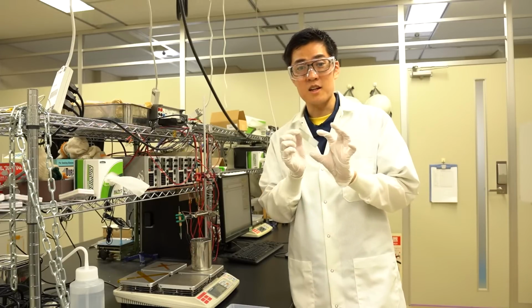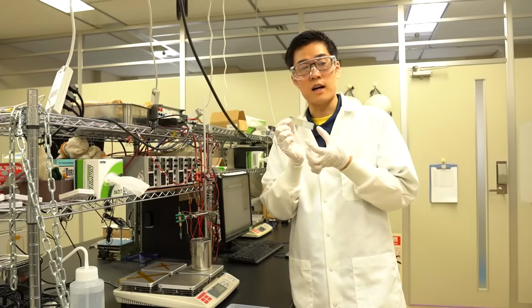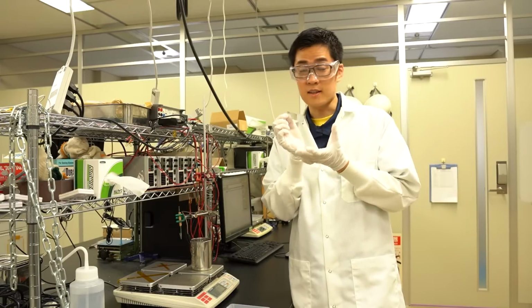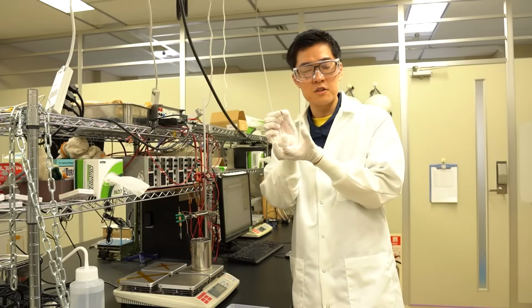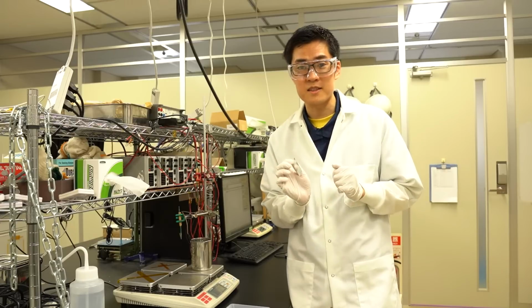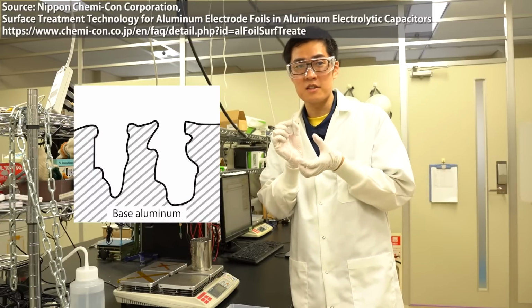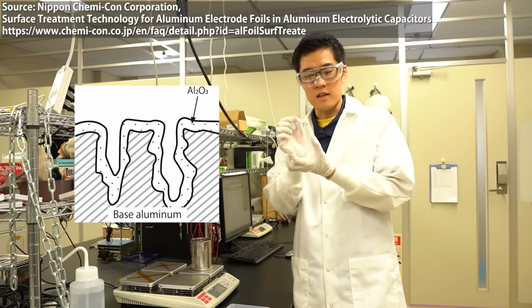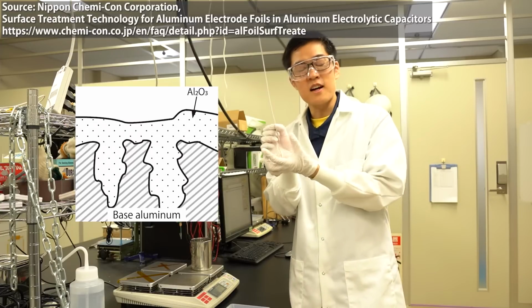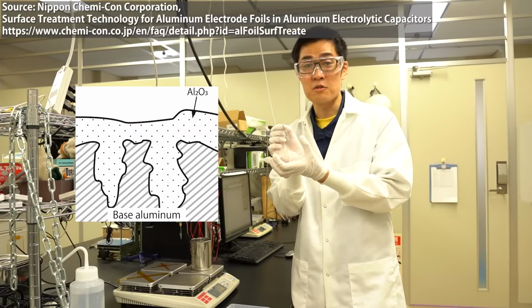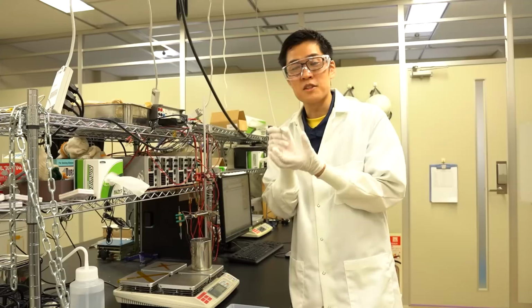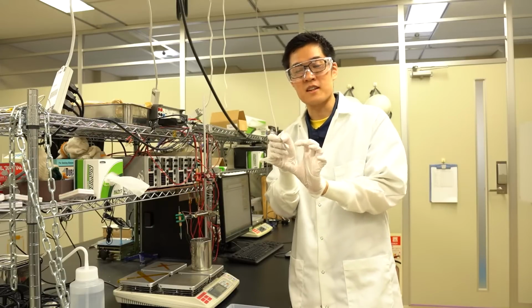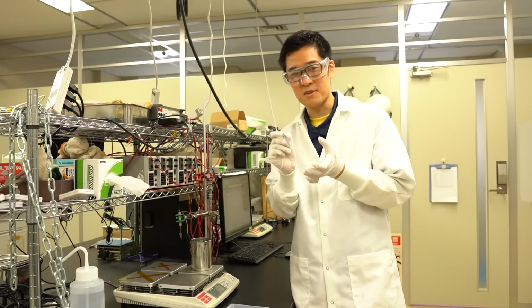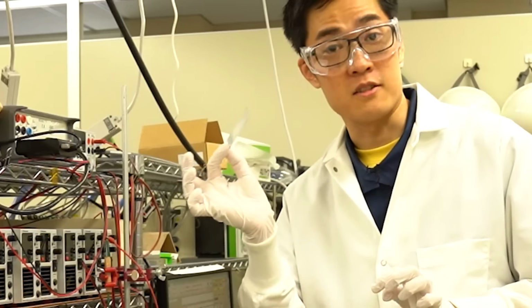An oxide layer is formed in the forming process. If this oxide layer is thick, the withstand voltage will be higher. If the oxide layer is thin, the withstand voltage will be lower. However, if the oxide film is too thick, the pits created in the etching process will disappear. Then, you won't be able to make use of the expanded surface area. Therefore, it is extremely important to form the oxide layer while keeping the balance between the withstand voltage and the surface area.